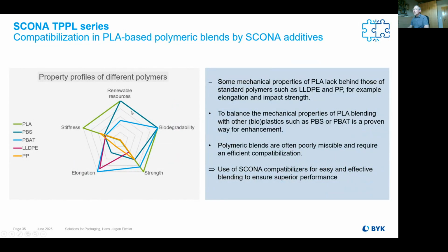Here, this slide should show you or give you an idea what are the benefits with the PLA. And of course, like I said, the mixture with a PBS or PBAT can help to improve the weaknesses from the PLA. So as you see, it's very strong in stiffness, has some weaknesses in case of the elongation at break, but here might be helpful to do a combination with a PBAT or with a PBS. So that is what the people still doing outside, right? They're doing combinations with different bioplastics to improve the balance for the PLA.